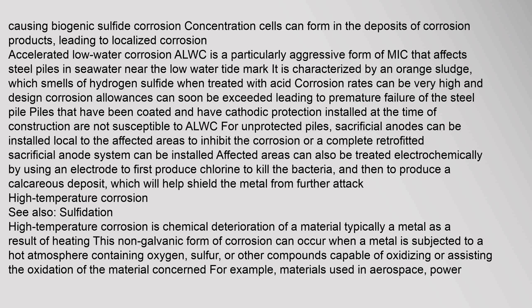Accelerated low water corrosion (ALWC) is a particularly aggressive form of MIC that affects steel piles in seawater near the low water tide mark. It is characterized by an orange sludge which smells of hydrogen sulfide. When treated with acid, corrosion rates can be very high and design corrosion allowances can soon be exceeded, leading to premature failure of the steel pile. Piles that have been coated and have cathodic protection installed at the time of construction are not susceptible to ALWC. For unprotected piles, sacrificial anodes can be installed local to the affected areas, or a complete retrofitted sacrificial anode system can be installed. Affected areas can also be treated electrochemically by using an electrode to first produce chlorine to kill the bacteria, and then to produce a calcareous deposit which will help shield the metal from further attack.